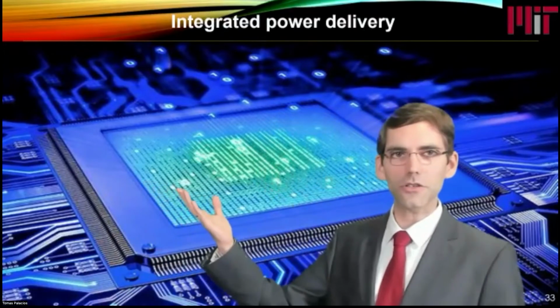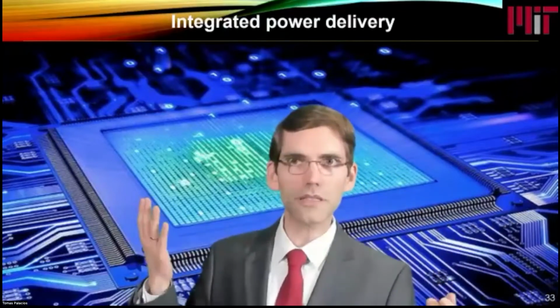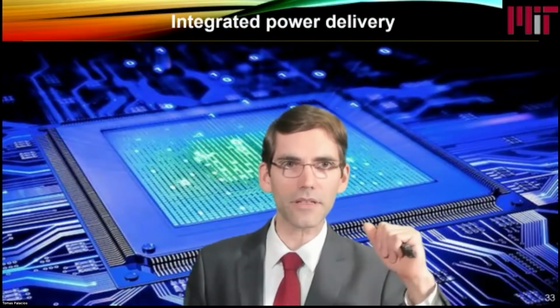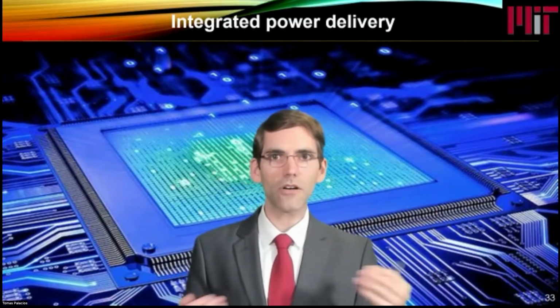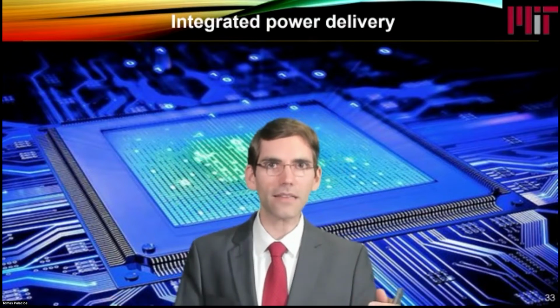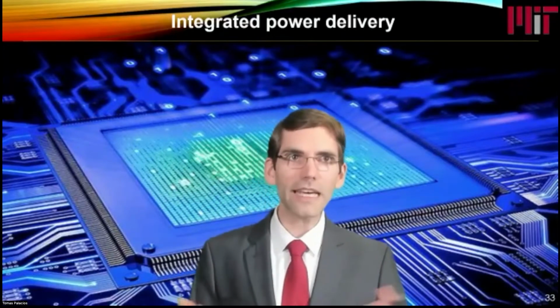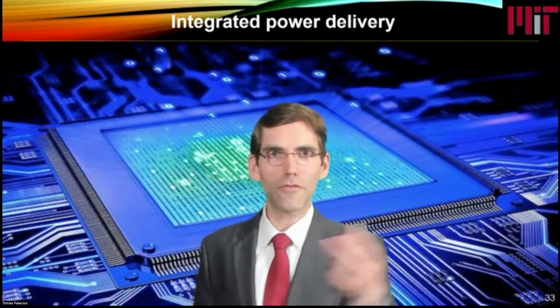For example, in a microprocessor, you need to introduce the power at low voltages and high currents because the transistors in silicon can only take a couple of volts of maximum drain voltages. So you introduce it at low voltage, extremely high currents. When you have these very high currents, in the range of a few hundred amps, going into a tiny microprocessor, any resistance that you have through those very narrow wires in the microprocessor is going to dissipate a very significant amount of power. In fact, around 40 to 50% of all the energy dissipated in a microprocessor is not dissipated by transistors switching on and off and doing computation. No, 40 to 50% of all the energy is dissipated as heat by current flowing through wires.